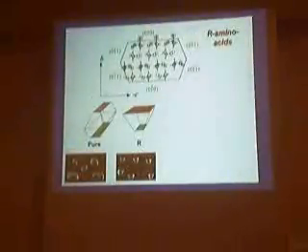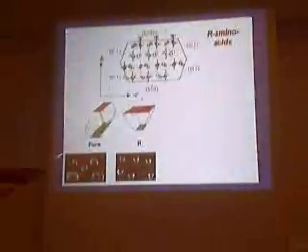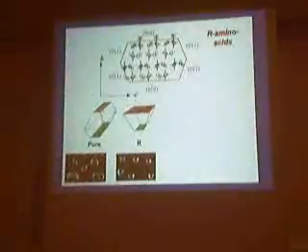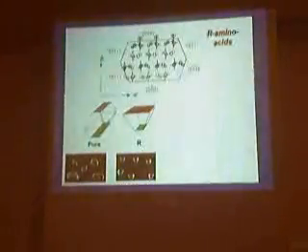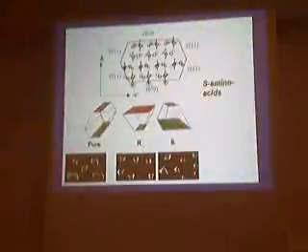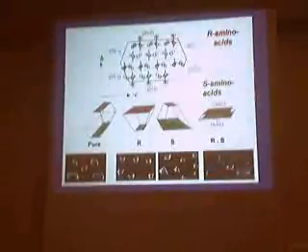Okay. So this is what we have here. We can learn about morphology. If you grow these crystals in pure water, you get bipyramids. Okay? If you grow these crystals in the presence of R, you get an enantiomorphous pyramid. If you go with the S, you get the other one, and if you go with DL, you get a plate.